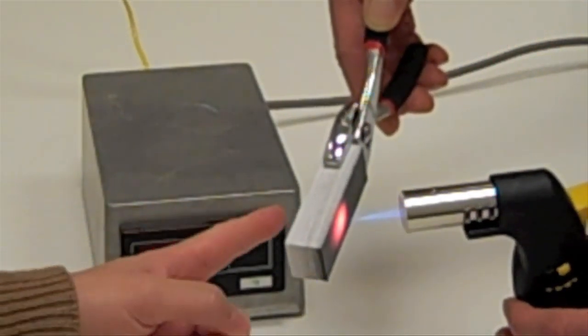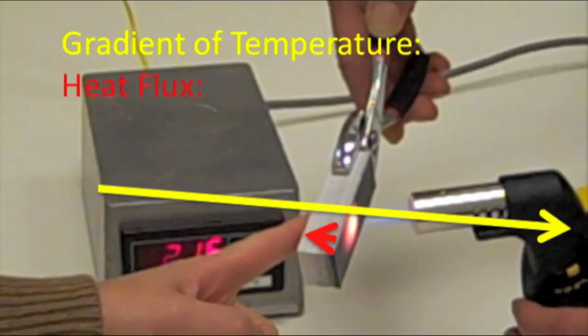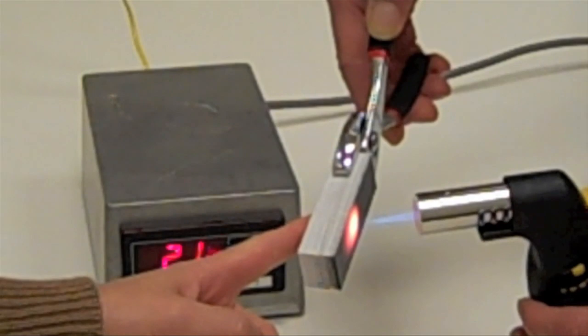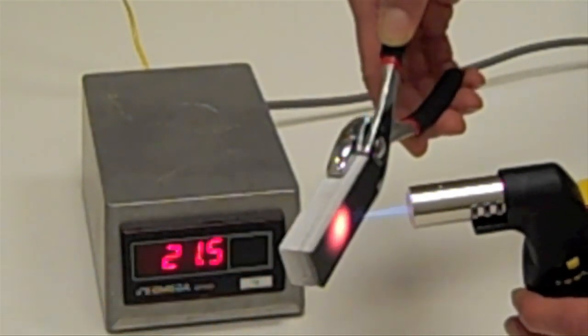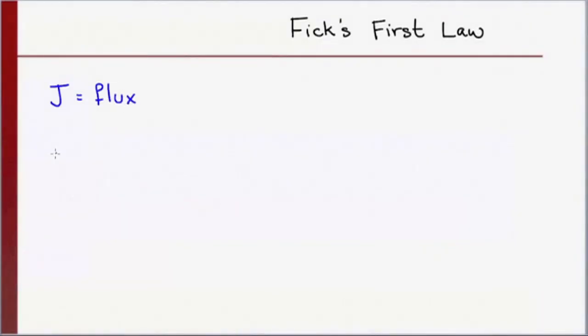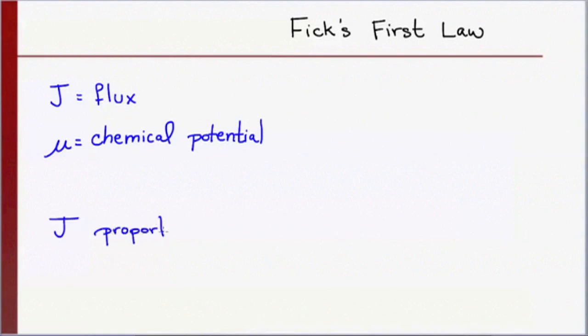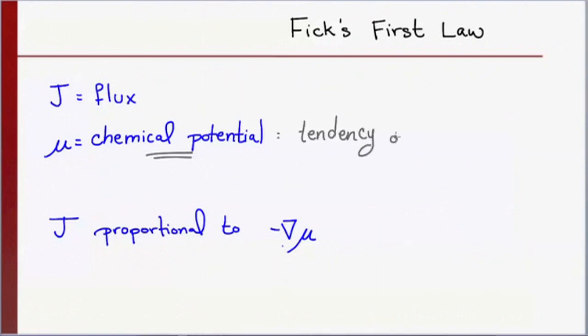The temperature gradient in the tile is therefore very large. There is a heat flux through the tile opposite in direction to the very large temperature gradient, but the flux is so small that the tile barely feels warm to the touch. Be aware that this is just one form of Fick's first law. The most general form says that flux is proportional to the negative gradient of the chemical potential. You may see the equation in this form in later courses.